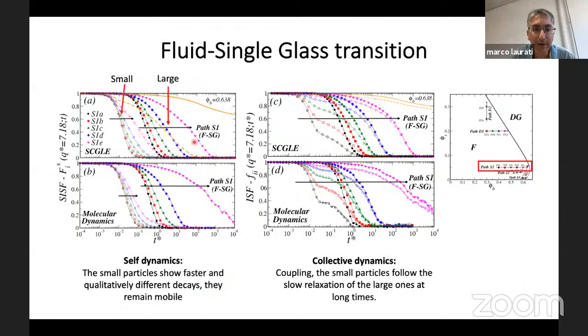And what you can see while approaching the single glass transition is that the dynamics of both species tend to slow down, but the dynamics of the large particles, when we come close to the glass transition, slow down much more than those of the small particles. So there is a clear decoupling between these dynamics. While when we look at the collective dynamics, we can see that, while approaching this transition, the dynamics of the two species become more and more coupled, which means that the small particles follow the slow relaxation of the large particles in the system.